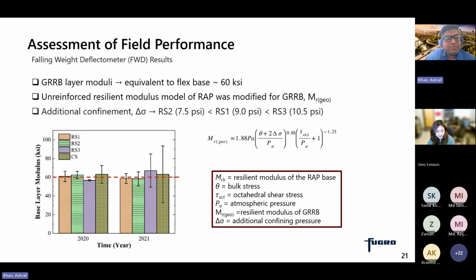We can also compute the additional confinement offered by the Geocell by modifying the material model with Geocell, and we can see the additional confinement for the RS2 was 7.5 psi, RS1 had additional confinement of 9 psi, and RS3, with the highest Geocell thickness in total, had the average increment of confinement of 10.5 psi with the Geocells.